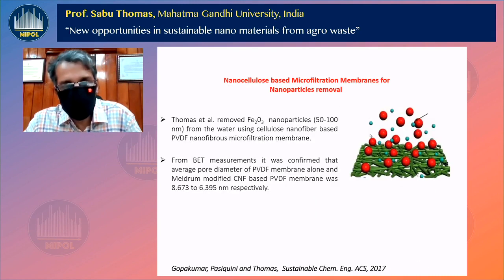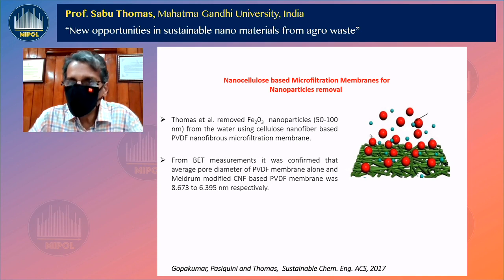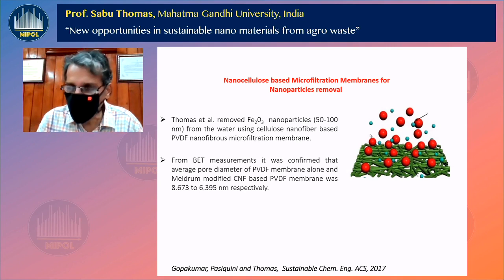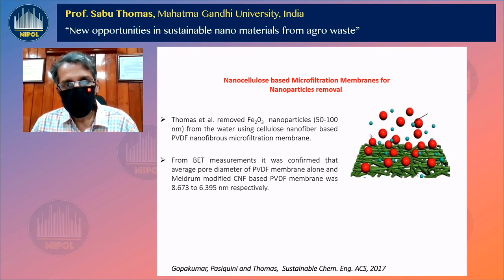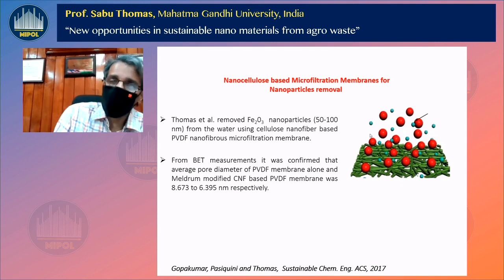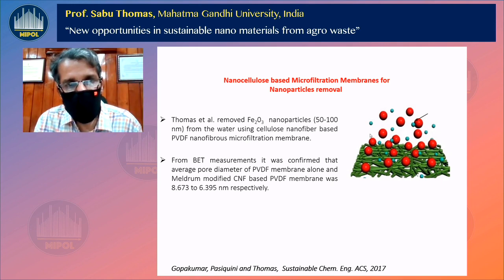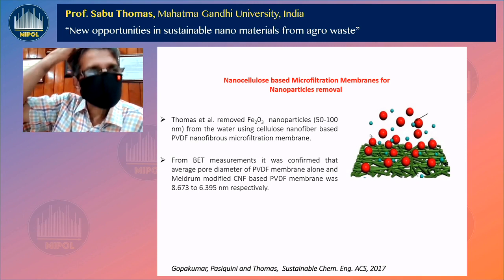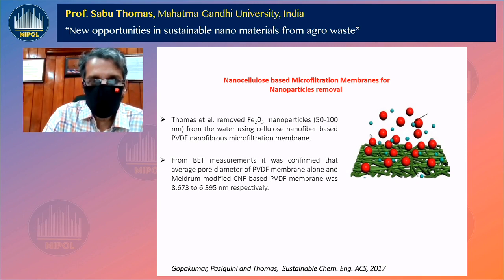Now let me show you another interesting thing my PhD student did. Probably you all know that water is increasingly contaminated with lots of suspended particles. It can be nanoparticles, microparticles. What we did is, we tried to pass all this impure water through the filter. And dear friends, when you give a coating of nanocellulose on the surface of this filter, the pore diameter is something like 8 nanometers, so small. So most of the suspended particles could be retained on the surface.